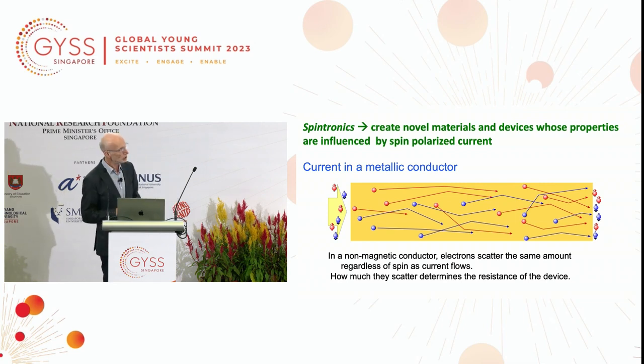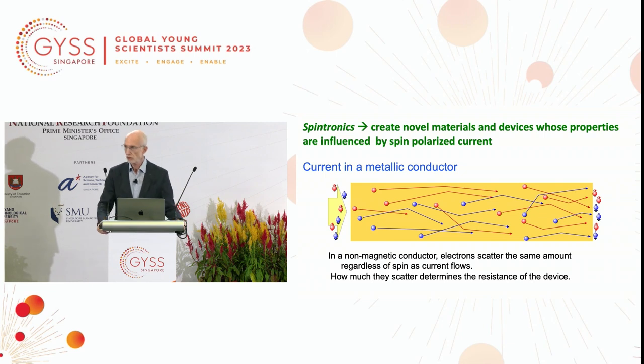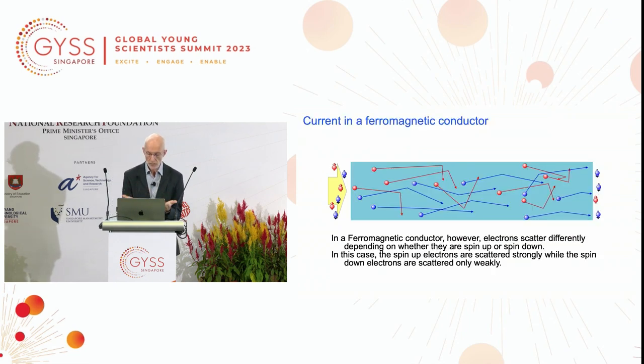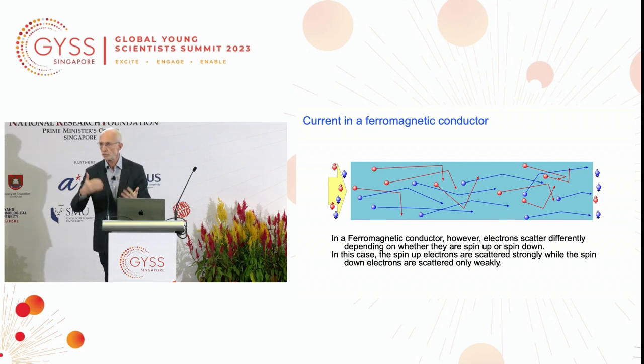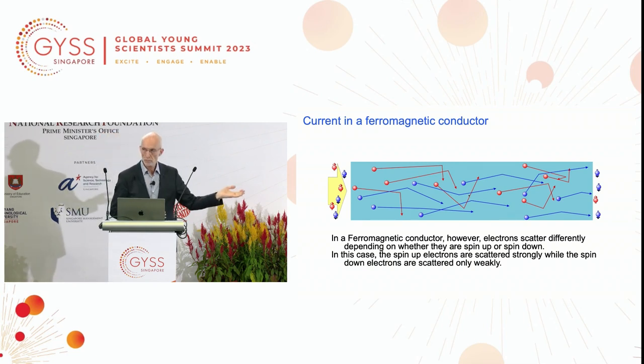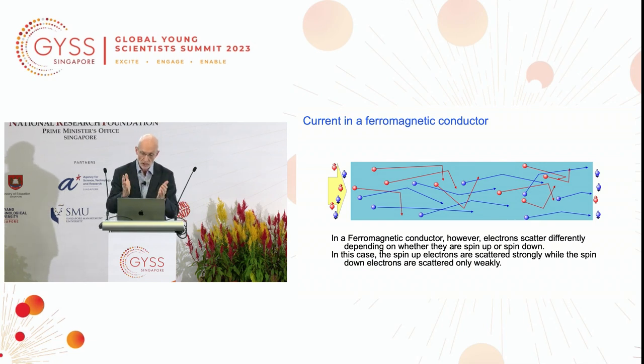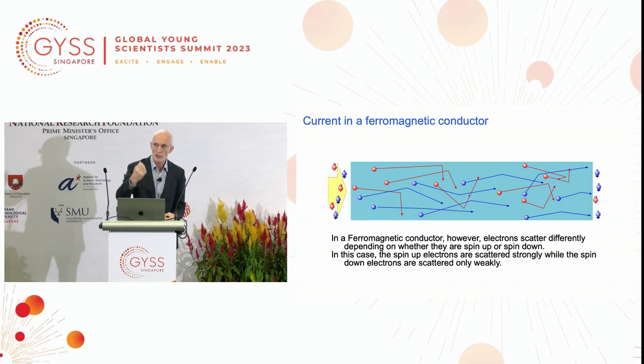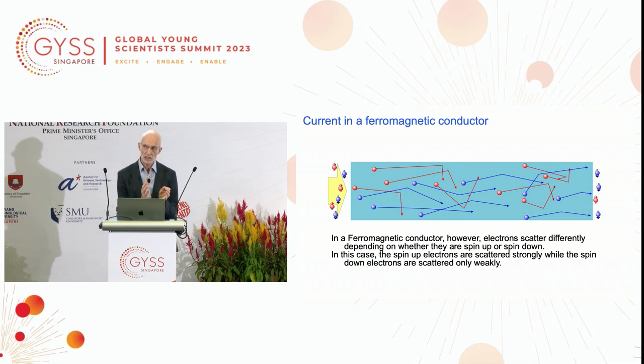If you take a non-magnetic metal like copper and you introduce from a battery a current consisting of equal numbers of spin up and spin down electrons shown as these blue and red dots, then the current is carried equally. The current is not spin polarized. However, if you take a magnetic material, let's say this blue material, could be iron, it could be cobalt, it could be nickel, you introduce this unpolarized current from a battery, and within a few scattering lengths, as the electrons scatter from the magnetic moments which are oriented in a particular direction, electrons with one spin are scattered more than electrons with the opposite spin. This leads to a current that is innately spin polarized.